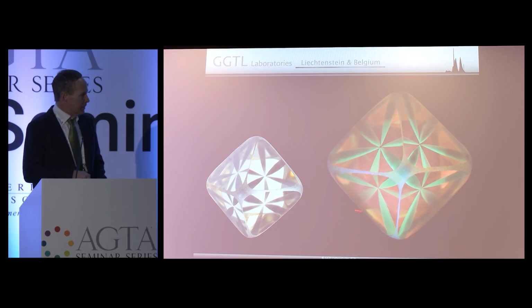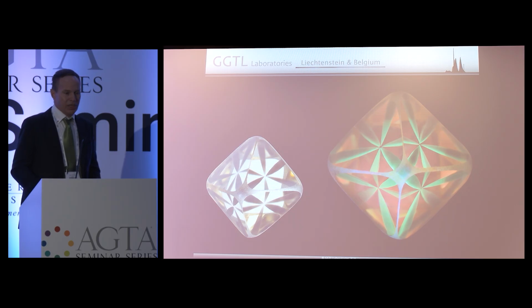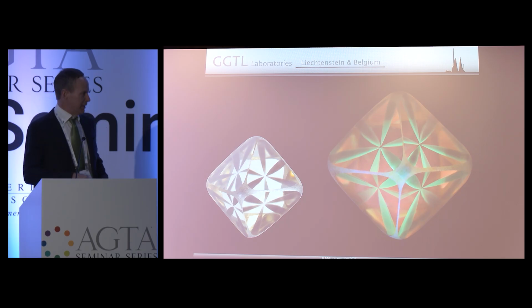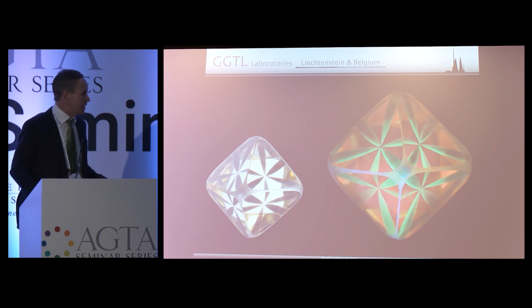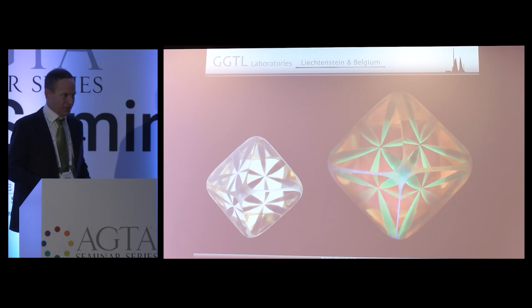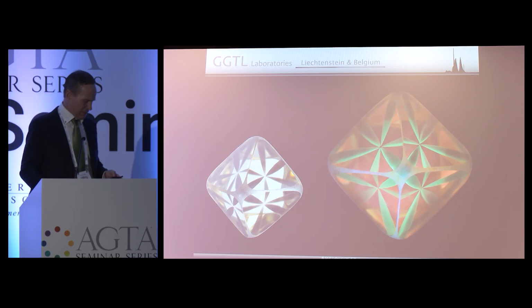Here, we're in the lucky situation that the stone actually fluoresced this beautiful orangey, pinkish, kind of reddish color, which is just a modification of the N3 center with an additional band in the red that causes this interesting fluorescence. And this gives us this beautiful contrast between the two colors. So whenever you see these stones, if you want to have fun with fluorescence, you buy some Zimbabwean material. That stuff is always rather spectacular under fluorescence.